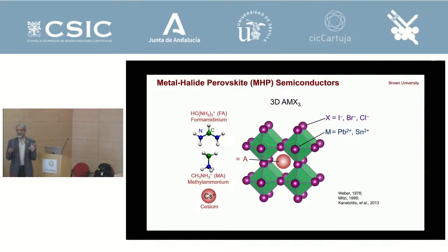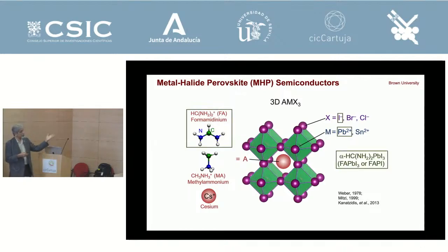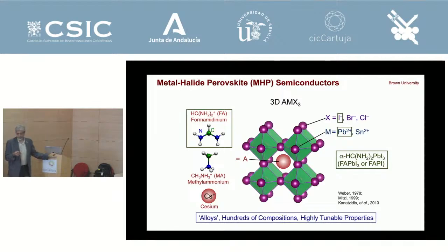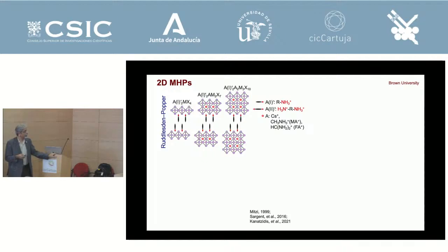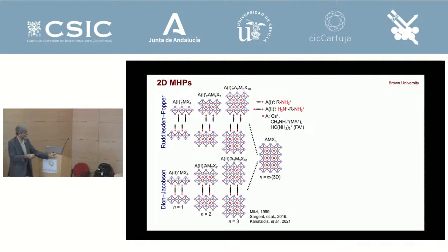But these are very fascinating materials called hybrid or inorganic-organic, right? And so that would be a typical composition we would use, FAPbI3 or formamidinium lead iodide, right? And so there are hundreds of compositions, as you can see. There are lots of combinations here, right? But also, this is the specialty I showed you, but we can actually have what are called two-dimensional perovskites. So you can have layers, one layer or two layers or three layers that are bonded by organic ligands. And so these are called Dion-Jacobson or Ruddlesden-Popper phases, right?